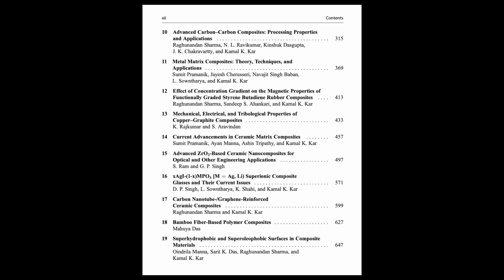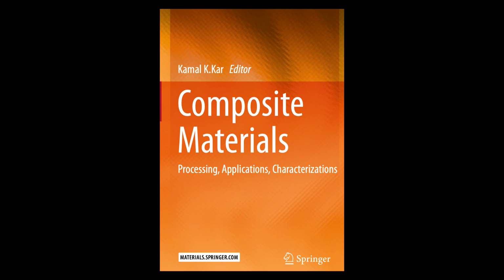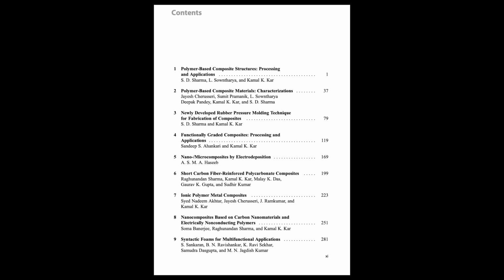Measuring magnetic properties, saturation magnetization, coercivity, remanence, tells you about particle dispersion and interaction with the rubber. What did they find? Magnetization varied with iron loading and position, as expected. Comparing graded samples to uniform ones showed the effect of the gradient. It's using magnetism as a tool to characterize these advanced polymer composites. Interesting approach. Finally, ceramic matrix composites, CMCs, for extreme environments again.